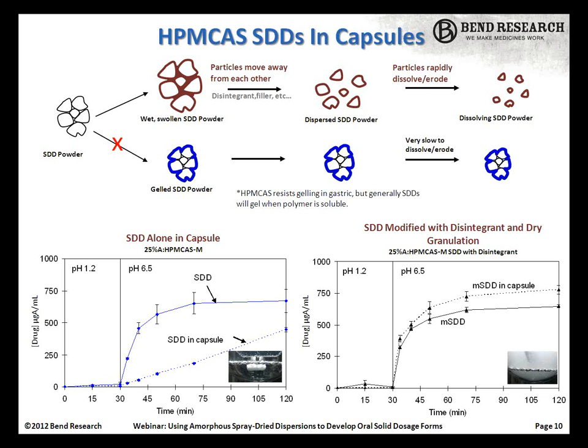If you take and you reformulate this dispersion in with some disintegrants and some additional fillers, what that allows you to do is just to disperse and granulate the material. Allows you to disperse the powder better when it comes into contact with the water. Then that's allowing the dispersion to go back to its native particle sizes and allow it to dissolve and take advantage of the small particle size in the rapid dissolution.